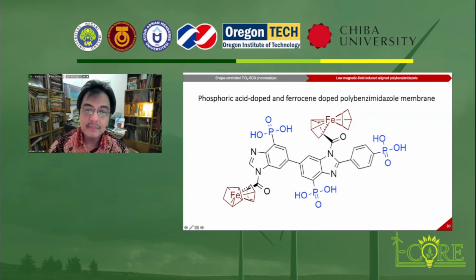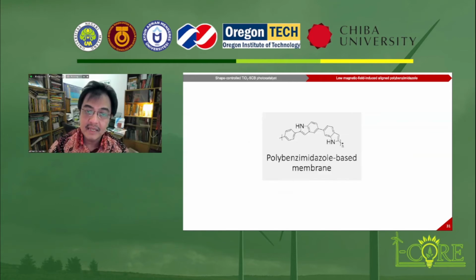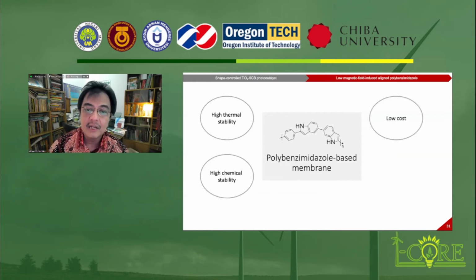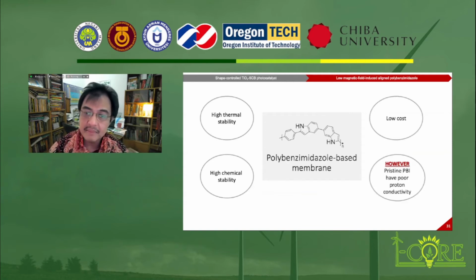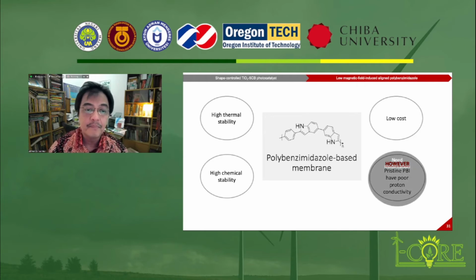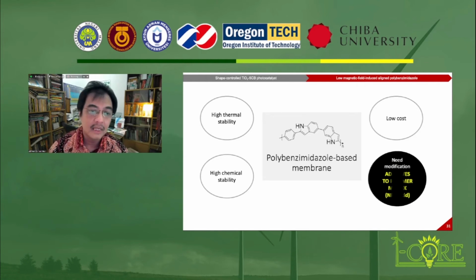Polybenzimidazole membranes attract attention because this material has high thermal stability, high chemical stability, and also low cost. However, pristine polybenzimidazole has poor proton conductivity and needs to be modified by adding additives or acids. Usually, to improve the conductivity, we need to add an additive to the polymer matrix.